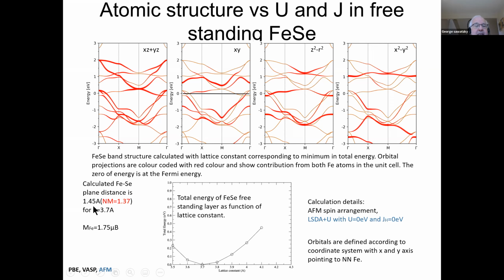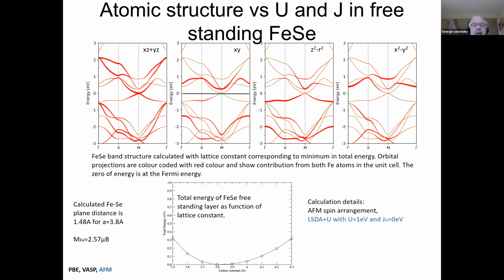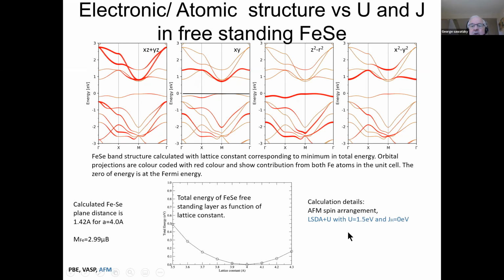Okay, and by the way, the distance of the selenium to the iron plane now is 1.45 angstroms, whereas in the non-magnetic case, it was 1.37. So this shows you exactly this effect of the elongation of that bond simply because you're occupying antibonding orbitals. And if you switch on a small U, 1 eV, it changes completely again. And if you switch on a U of 1.5 eV, it changes again completely, and you have a huge gap. Remember, your Fermi energy here is always put at the top of the valence band, okay? So in DFT, that's the usual way of doing it.